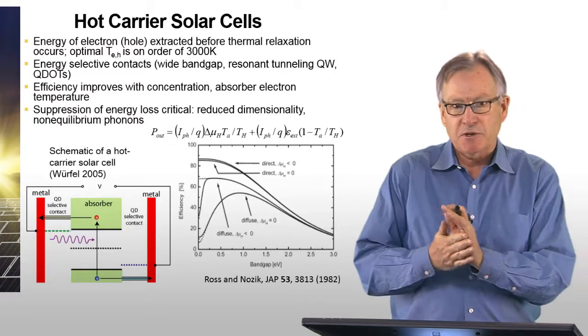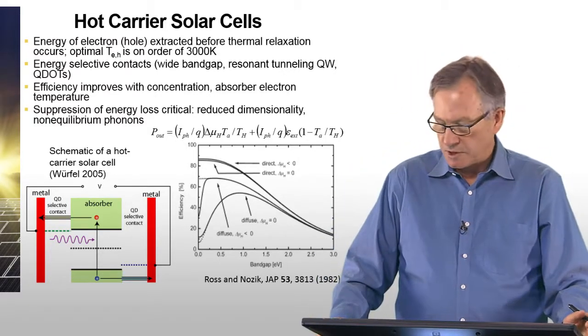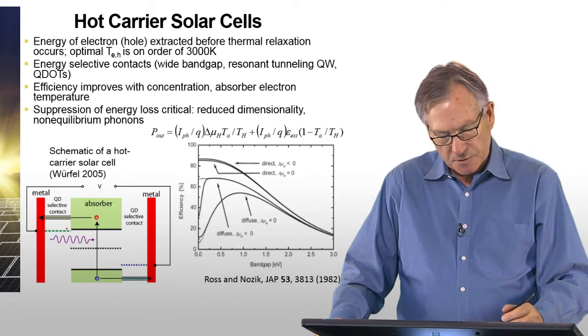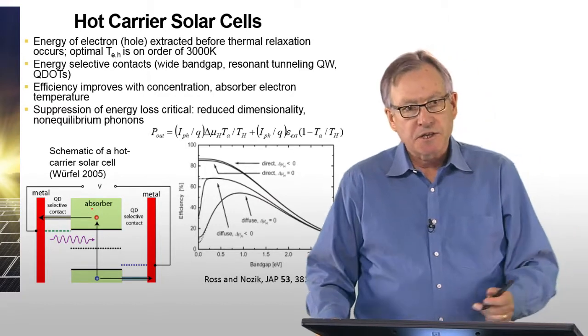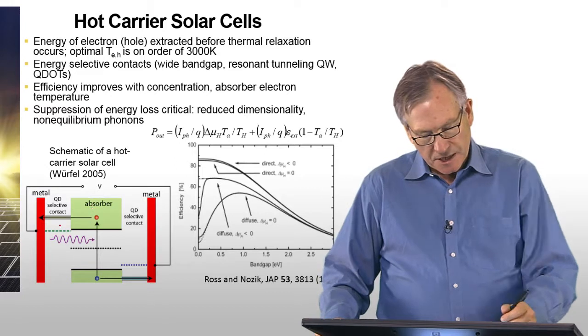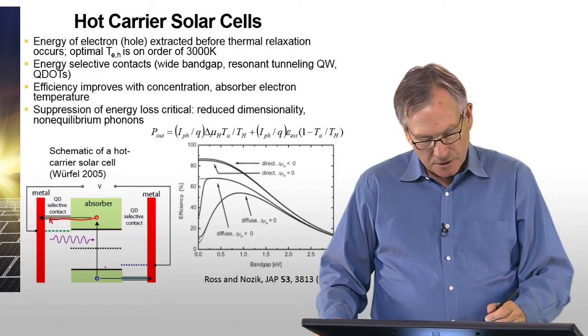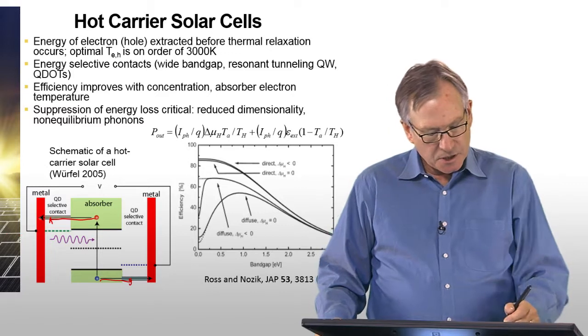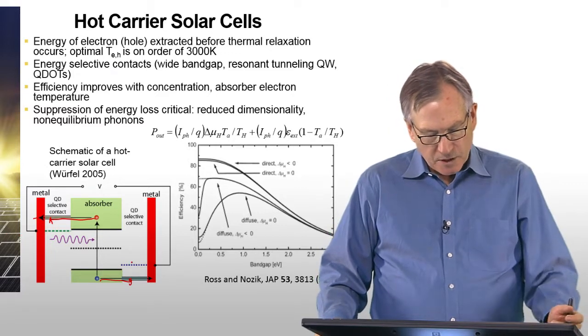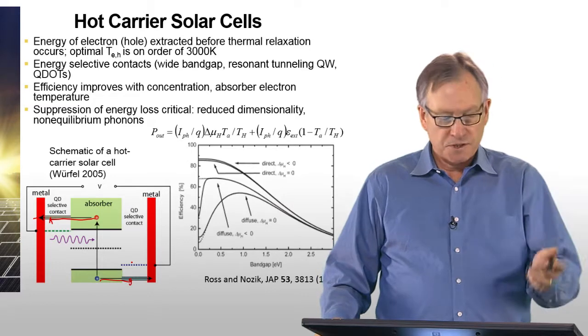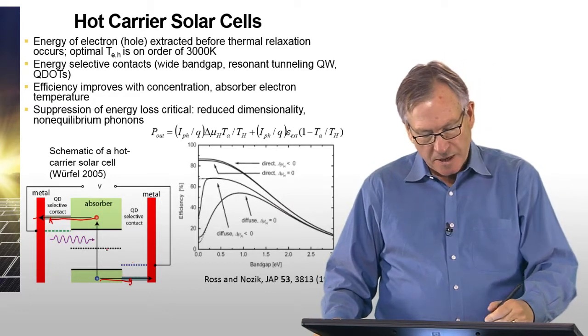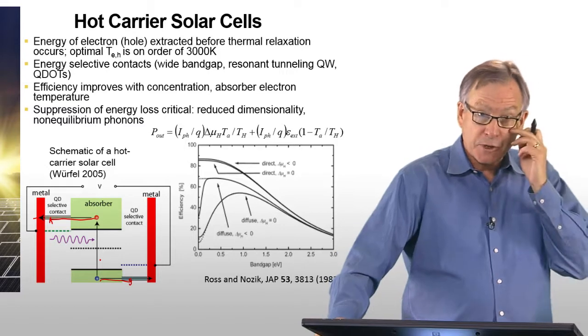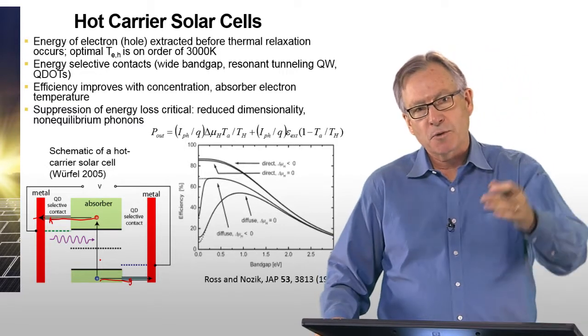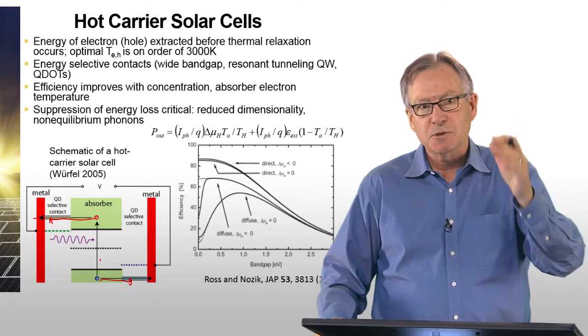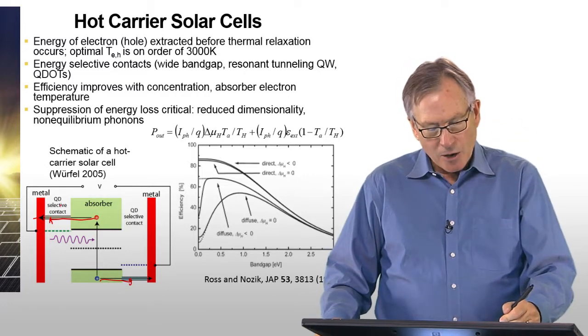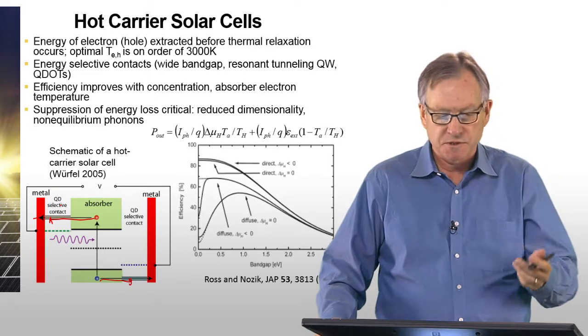So the last topic I want to talk about is that of the hot carrier solar cell device. I already introduced this architecture before, and that is that you have an absorber where there's no energy loss. The carriers stay hot, and they have enough energy to tunnel out or go through these energy selective contacts and be collected in a metal. So you have a voltage that's determined by the energy selective contacts, not by the band gap of the semiconductor in this case. So you're utilizing the energy of the hot carriers before they have time to relax. You're harvesting this energy before it's lost to thermal processes.